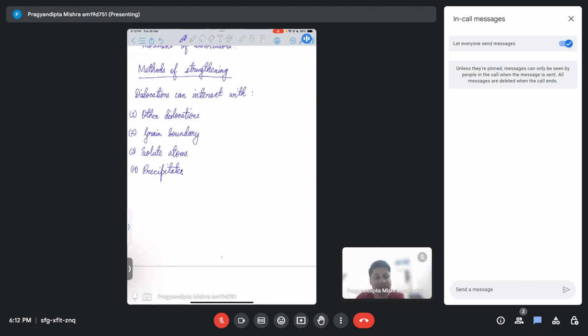Okay, so now this aluminium can also mix with the matrix element, that is magnesium, and together they can form some extra particles which might come out as a separate phase, so that the limit of aluminium within the matrix remains within the threshold. So this extra phase comes out as a separate particle, and that is something known as a precipitate. Now these precipitates are very, very important in material behavior studies, mainly because they help us in influencing the behavior in a lot of different ways. One of the best ways is, of course, by restricting the motion of dislocations. So you can think of precipitates as extra phases or particles present within the material structure, which help in influencing the overall material behavior.